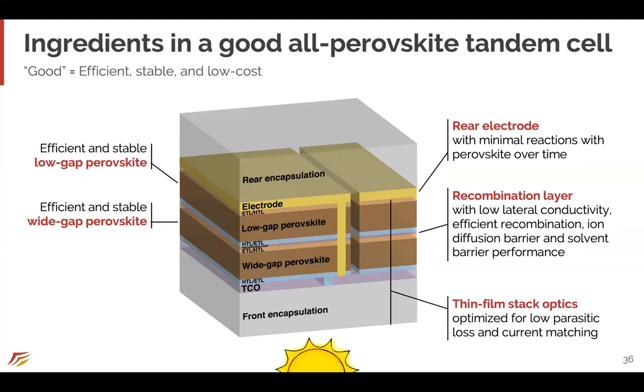And finally, the optics are really important here. So if you change the short circuit current a small amount in a tandem, it actually has a much bigger impact for tandems than for single junctions. So we need to optimize the layer thicknesses and optics to reduce optical losses and match the subcell currents. Now that's obviously true for a two-terminal primarily, for the current matching at least. So obviously this whole stack needs to be made using low-cost materials and manufactured at high throughput.